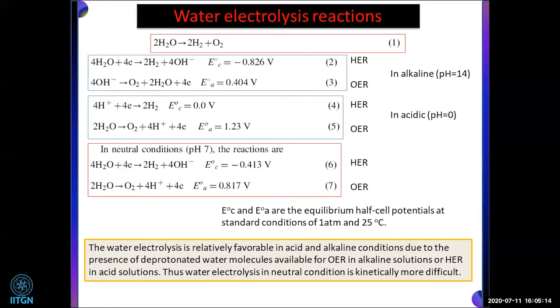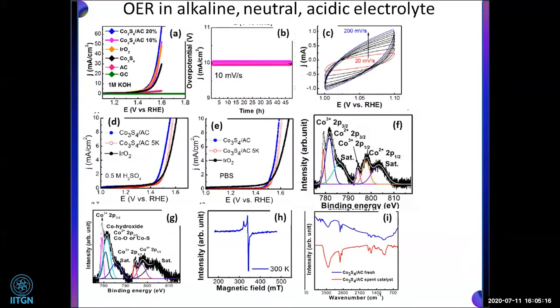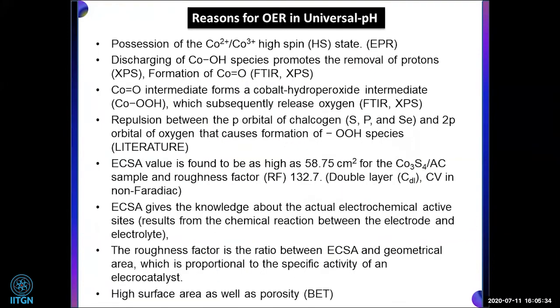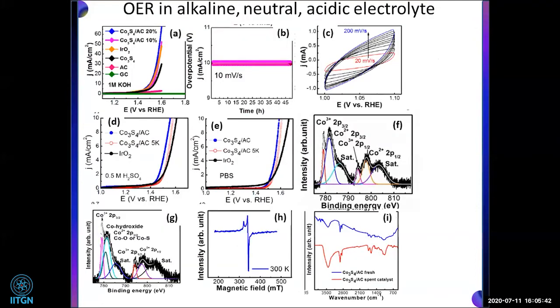So what happened here? If you see, this is the OER reaction in KOH. This is the OER reaction in H2SO4, and this is in PBS, neutral medium. And this reaction goes for 48 hours. So we tried to understand the mechanism. What is happening here? Let's see. The first thing is the presence of cobalt 2+ and cobalt 3+ high spin state, which we got from the EPR study.